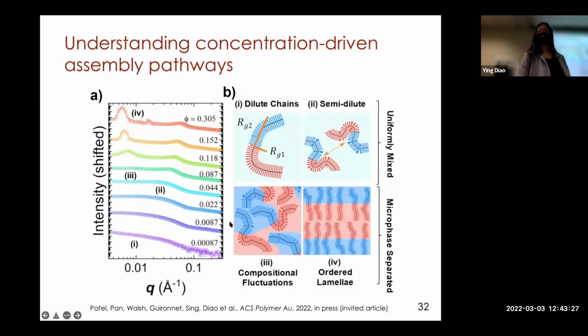we want to understand how this process works so that we can better design the printing processes to control structural color. So essentially, we figured out that the assembly pathway is driven by concentration. Basically, when we increase the concentration of the polymers as the solvent evaporates, we drive the polymer to assemble into these microphase-separated structures. And what's important is that in the later stage of assembly, the polymer becomes straighter and straighter. So the spacing at the nanoscale becomes larger and larger. So basically, we're evolving from blue to red during the assembly process.